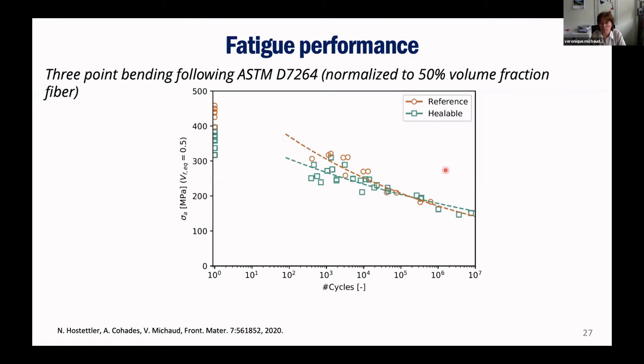And then we also did some fatigue. And by then, I should say, I might have decided not to do a postdoc and to stay and make a startup company and really go into trying to bridge and get this material into application. So we did some fatigue performance. We saw that compared to the reference system, this is all normalized to 50%, because our system was a bit less than 50% at the time. But we see that the healable system has a little bit lower properties at low number of cycles, but actually crosses over, and our high cycle fatigue was actually quite comparable, even better than reference epoxy.